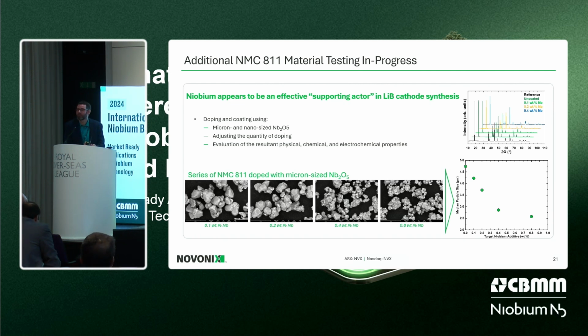And I'm just showing a really quick highlight of some early data of what we have seen with niobium oxide, micron-sized niobium oxide as a dopant material within NMC811. The most interesting thing that I take away from these data thus far is that the particle size of your NMC811 powder decreases as a function of increasing niobium dopant, which is very interesting. You can get a size control aspect out of using niobium oxide as a dopant material in NMC 811 that's synthesized by all-dry processing.